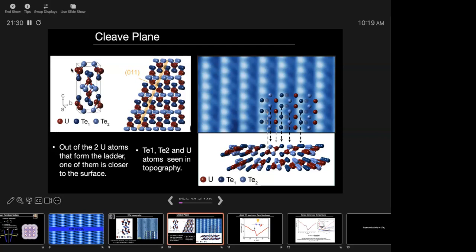And in fact, even though this topography is dominated by one of the tellurium atoms, it turns out you can see all three atoms that are close to the surface. This tellurium chain, this uranium chain, and this tellurium chain, we have access to all of that from the topography. Because if you Fourier filter out this one, you can see the other atoms.